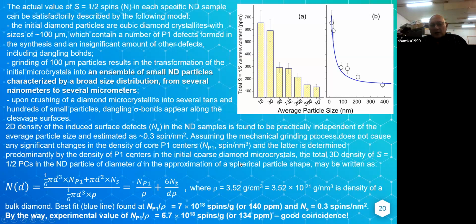And okay, applying this simple formula, you can see that this fit provides real numbers. The best fit is achieved for the density of P1 centers about 140 ppm and density of surface spins 0.3 spin per nanometer squared. And the experimental value is the same, 6.7 times 10 to the power 18 spins per gram, or 134 ppm. Very good coincidence.